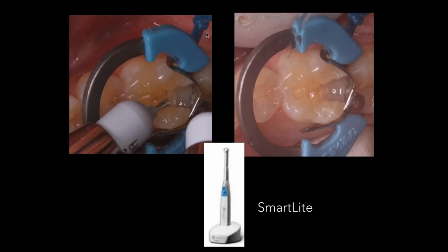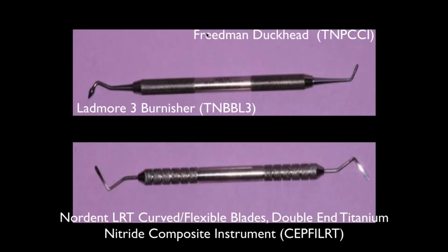Here I'm going to light cure this again for 20 seconds and make sure it's solidly cured. After I take off the ring and the matrix, I will cure from the buccal aspect into the gingival box, proximal box, and then we'll let that rest for a bit, and then again approach the curing from the lingual aspect into the gingival box as well.